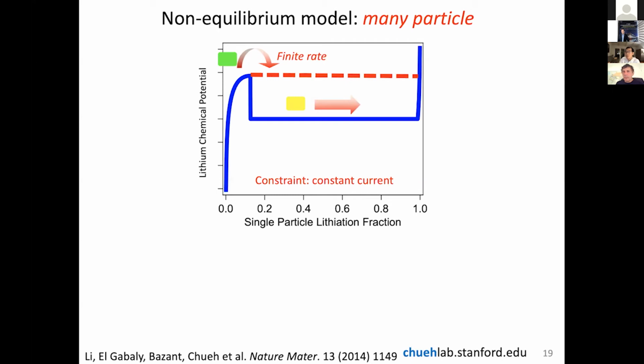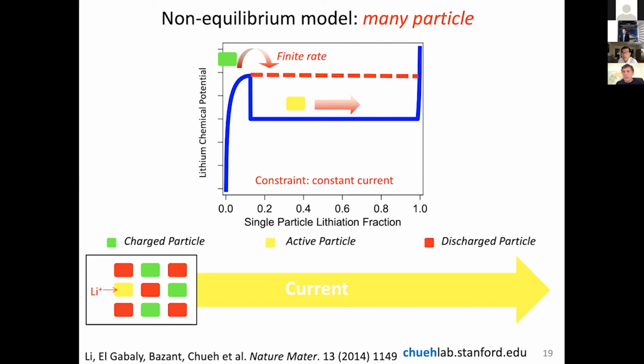And because of this requirement, this nucleation barrier pins the chemical potential or the voltage you are applying. So you have to constantly be at a potential that is greater than your nucleation barrier in order to keep the nucleation events coming. And then because of this pinning, that means the driving force, or the difference between the dashed red line and the blue line, is almost constant. Let me show you schematically what happens. So when the rate is very slow, when you're cycling the battery and intercalating very slowly, your red line is just slightly above the nucleation barrier.